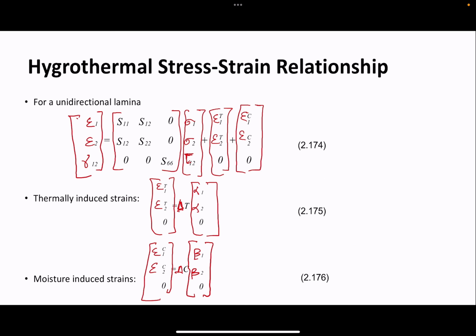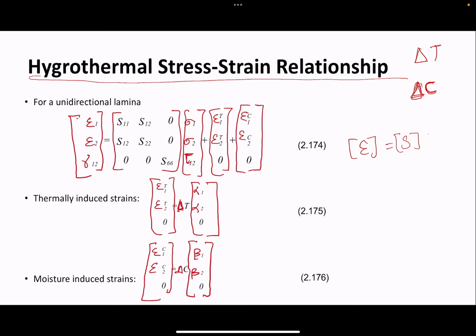The last part which I want to go over quickly is hygrothermal relationships. Hygrothermal meaning what happens when you have a temperature change, what happens when you have a humid environment. C here stands for moisture. If the moisture is being absorbed by the matrix mainly, what happens? So for a unidirectional lamina, this is the same relationship we have seen. Strain equals compliance matrix times stresses, correct? But here you add the strain caused by temperature change, expansion or contraction, and also the change caused by moisture absorption. So thermally induced strains epsilon T are equal to change in temperature multiplied by the coefficient of thermal expansion.